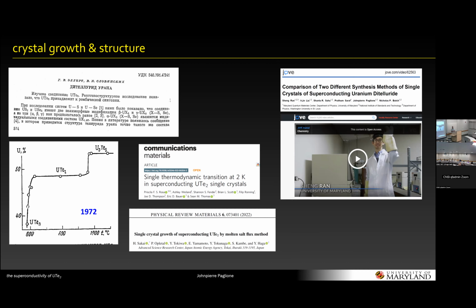Yes? Is there a relationship between these three different uranium tellurium phases? Can you understand how one transforms into the other, or are they really distinct? I just mean their crystal structures. They're quite different. So all I'll say is that there is at least one phase, I think a uranium-1, tellurium-1 that's cubic, and it has a lattice constant that might be close to one of the lattice constants of UTe2. So you can imagine there might be some crystal faults or something, but no one has observed anything yet.